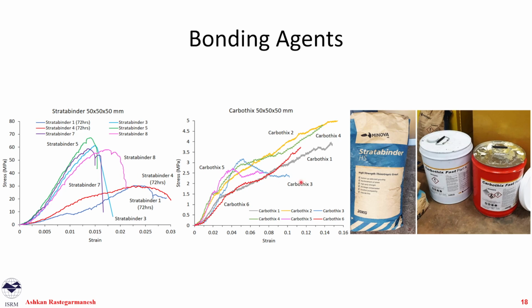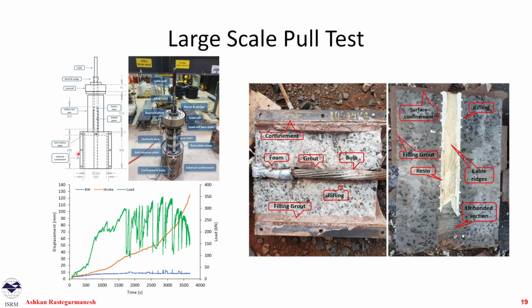This is the load displacement curves that we got for them, or stress strain curve for cementitious grout, which was a Stratabinder, a product of Minova, and our resin, which was a product of Minova, Carbothix. Again, Minova is another very big producer of this type of material, and these are the loads that we get on them. What's notable is that our resin type of failure is more like a strain hardening with much lower loads compared to our cementitious grout, which had a behavior very similar to cement or concrete.